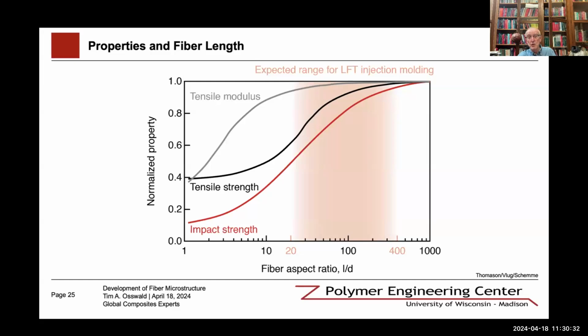So this graph here actually shows the effect of fiber length. Typically, we know that a fiber length, or L over D ratio, of 100 is the length that we should have to retain properties, but in many cases we don't even come close to that. So the fibers get damaged significantly, and we can go to 300 or so micrometers in length, which are L over Ds of maybe 15 or 30. So fiber attrition is significant.